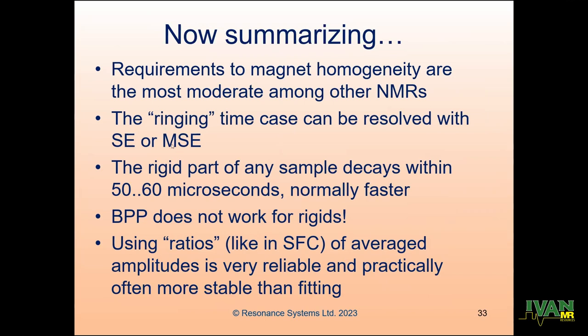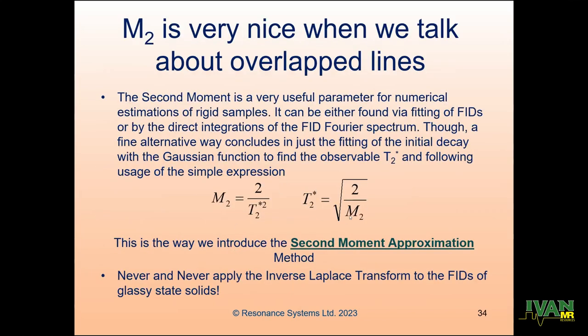It's quite linear. So it means that these approaches are working. So what's important practically? The rigid part of any sample decays within the initial 50 microseconds. This is very much important. Then another thing, classical theory about relaxation times does not work for rigid. This is absolutely a must to know. But what's funny is that sometimes you read a publication and you see them trying to use BPP for a solid sample. And what we are offering is the so-called second moment approximation. Use the second moment to characterize T2 of any sample without fitting.